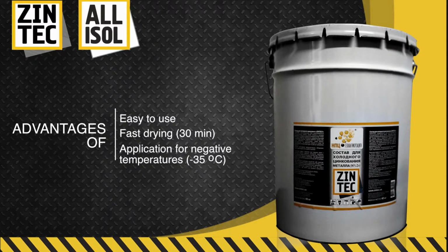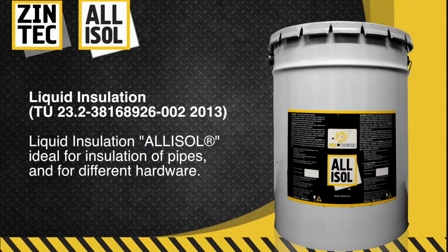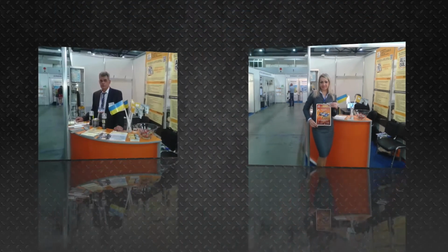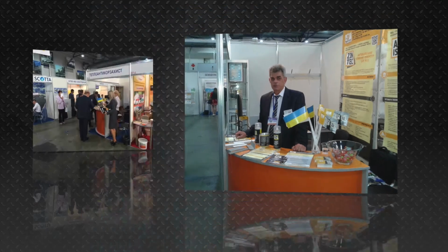It has an extremely high resistance among single component formulations in a hostile environment in accordance with the requirements. Corrosion tests on artificially aged zinc coating carried out under the influence of salt mist in accordance with ISO 7253 exceeded 1440 hours with a 3-layer coating without breaking.